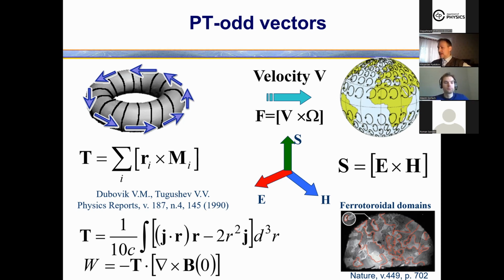Thank you. As a rule, in second harmonic generation, due to the polar nature of the toroidal and antiferromagnetic vector in this case, second harmonic generation is sensitive to the electric polarization, to the inversion symmetry break, and also sensitive to the antiferromagnetic vector ordering.